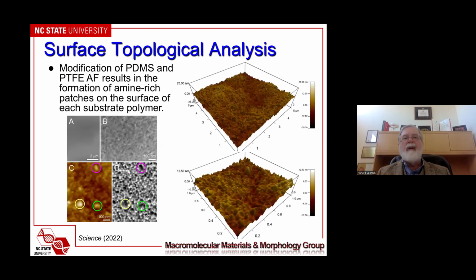These are complementary AFM images where we have the height and the phase image. Over here, height is light. Over here, phase, soft means dark. And so these protrusions that you see here are actually quite soft. So these are more or less patches of these grown chains, and you can see them over here as well. This is, by the way, an ultra high resolution SEM image showing the same kind of features.